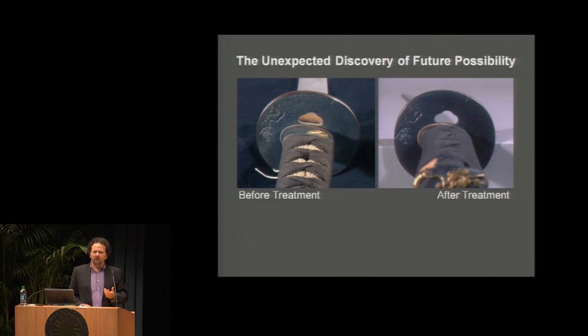So the tsuba of this particular sword had copper corrosion on the surface. It was patinated with a shakudo, so a very thin black patina on this very copper-rich material. I tried traditional mechanical cleaning. All it would do was take the patina off straight down to the copper substrate. It was not effective.